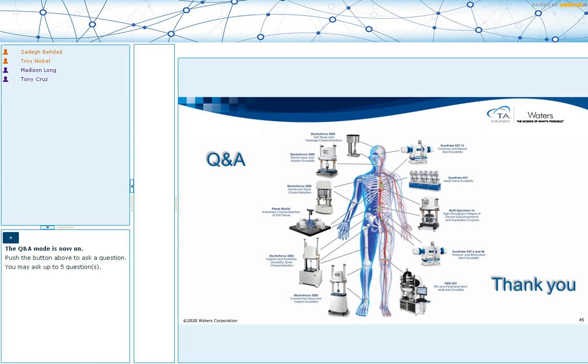So this is under what we would call a force control method versus a displacement control method, right? That's correct. Yes. You can tell your controller to apply deformation in two modes: either a displacement control mode, where you look at the load changes, or you can control the load and monitor displacement changes. So in this case, doing a load control test will be more helpful because, regardless of the height of your sample, you can make sure that you stay in contact.